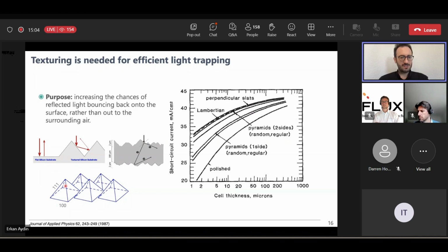We just slice the wafers aiming that the planar side is the 100 plane, because these are single crystal. And when we etch away, we form these pyramidal shapes on the front surface. And by tuning the size and the distribution, we can really minimize the reflection on the silicon cells. And as you see here, if we make a double-side texturing, we can really approach the Lambertian limit, and that's very good. This is also a standard thing in the industry, but the problem is now here.